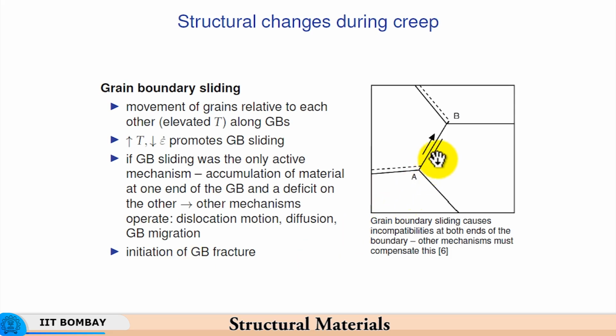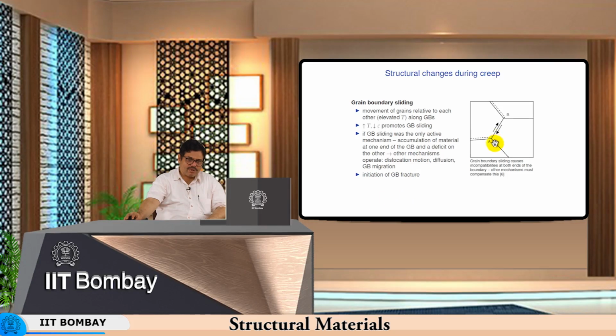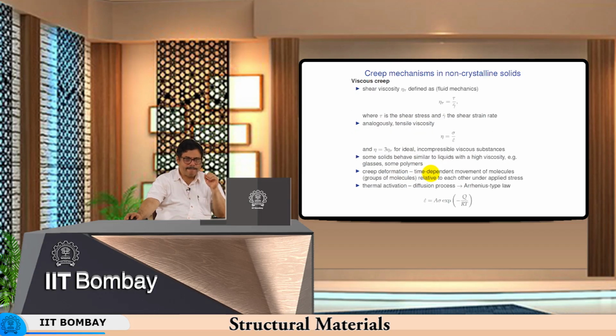So, if the diffusion does not match the rate of grain boundary sliding at some point, then fracture takes place, grain boundary fracture. So, in fact, the triple junction will start, because these three grains may start moving away, and then you will generate a void at this triple junction, which will propagate and finally end up as a failure. So, the grain boundary fracture finally will take place if the creep mechanisms do not operate in unison, or they don't compensate for each other adequately.